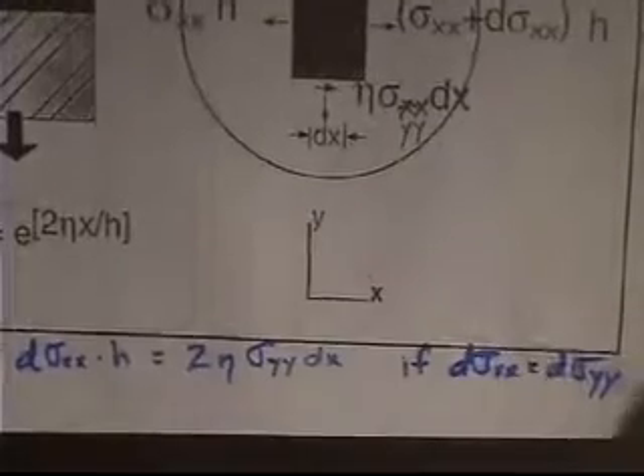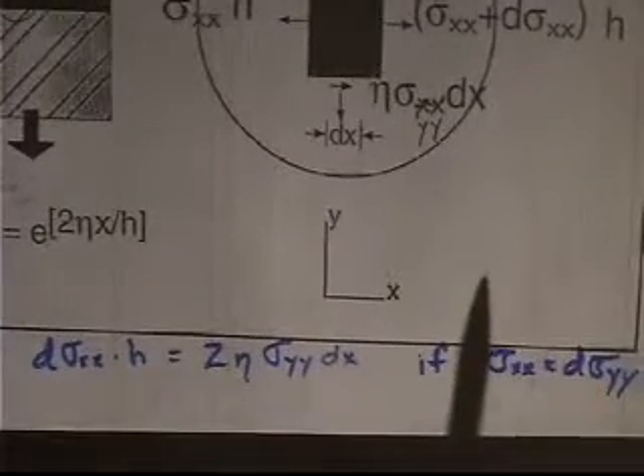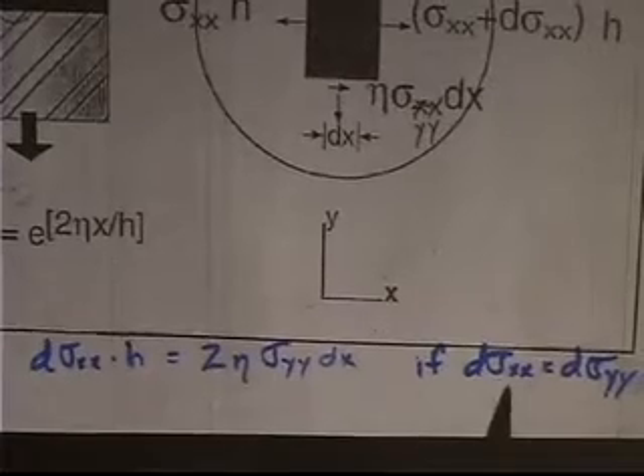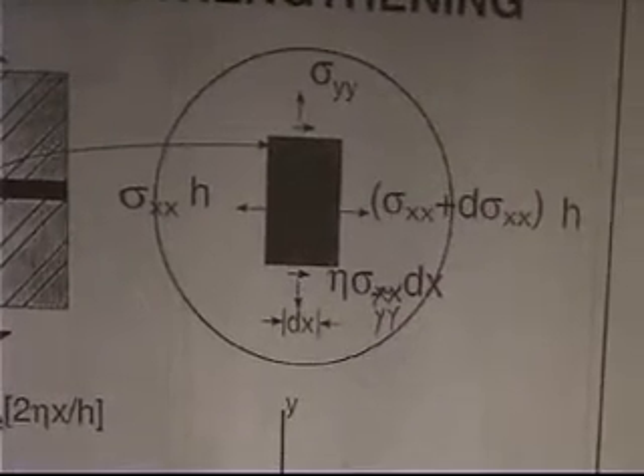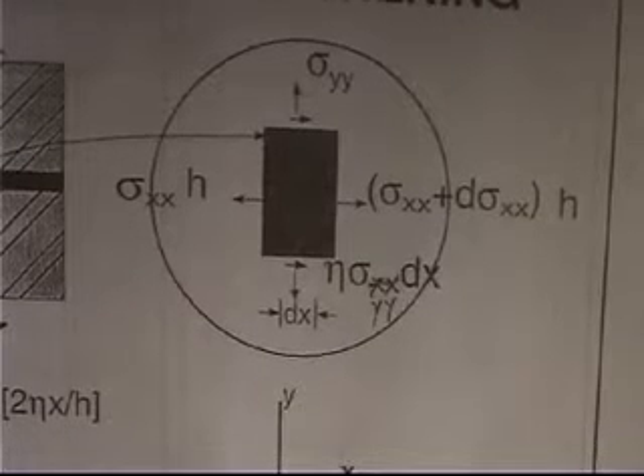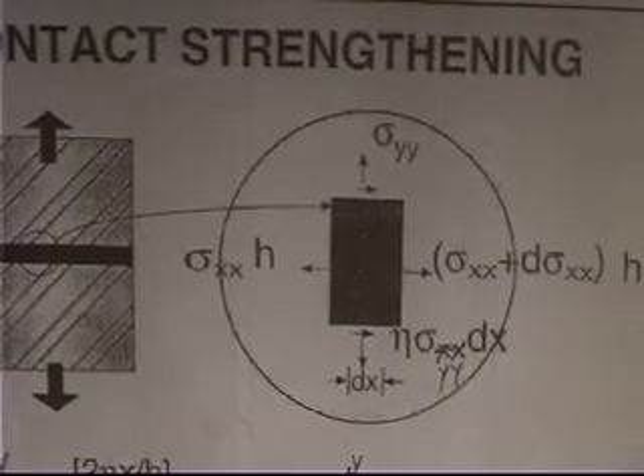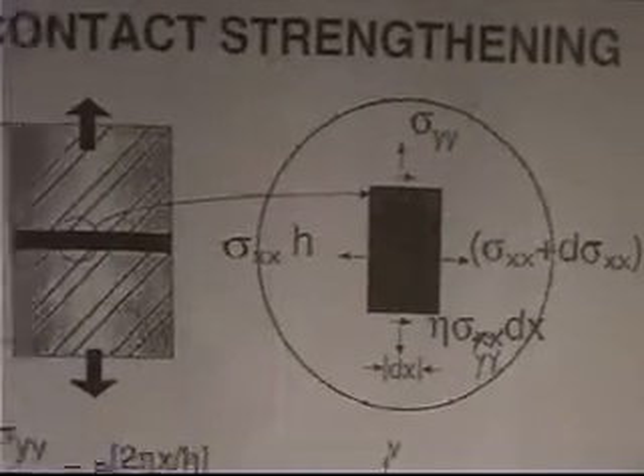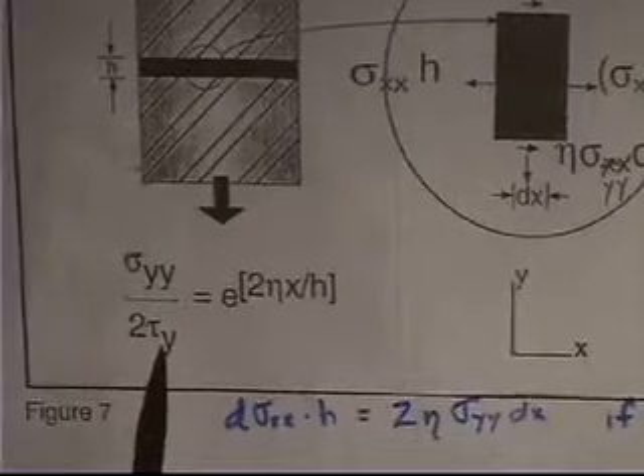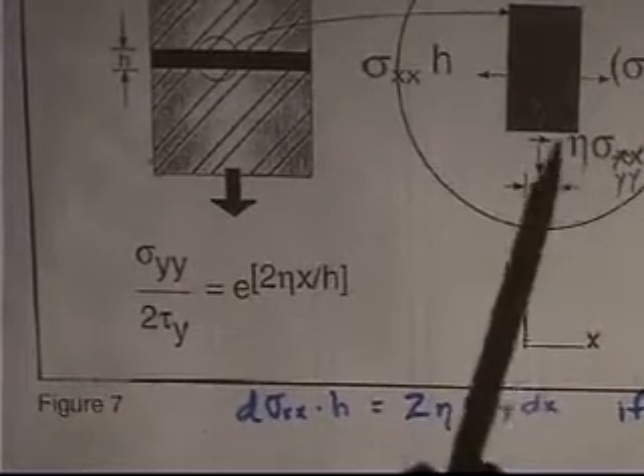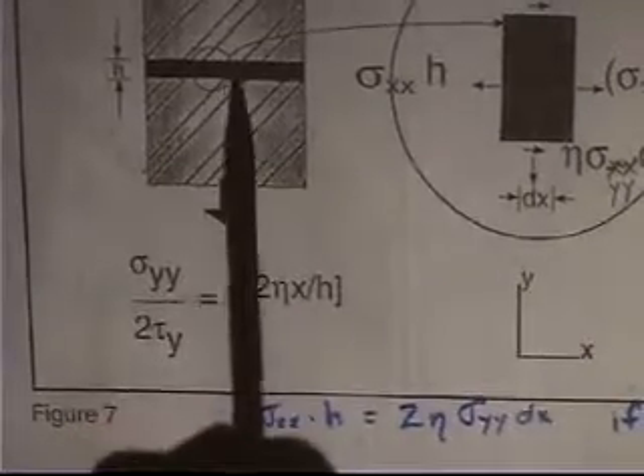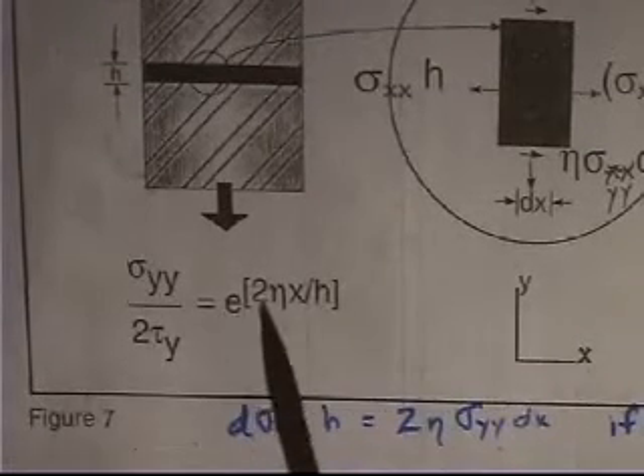And if these are principal stresses, and they're not exactly principal stresses, but they're pretty close, it turns out d sigma xx for a principal stress is equal to d sigma yy, so I can change this d sigma xx to a d sigma yy. And with that little prestidigitation, I end up with a solution to the differential equation of sigma yy over twice the shear stress of the material, which is the shear stress of the braze alloy, equal to an exponential 2 eta x over h, for whatever that's worth.